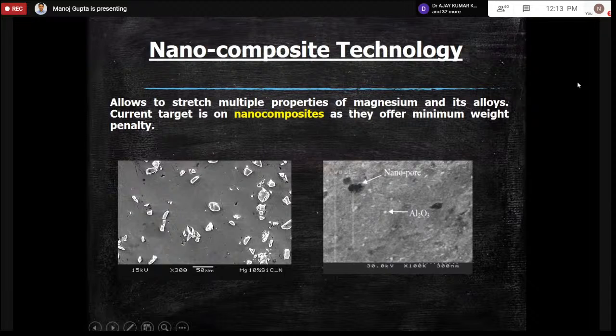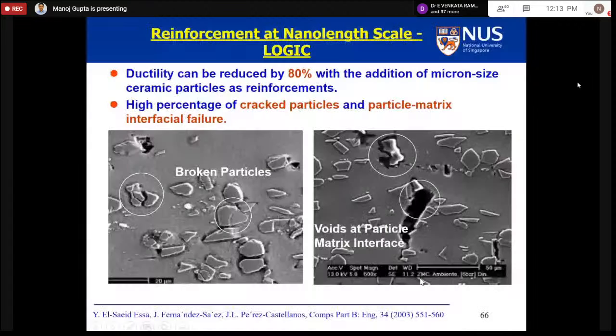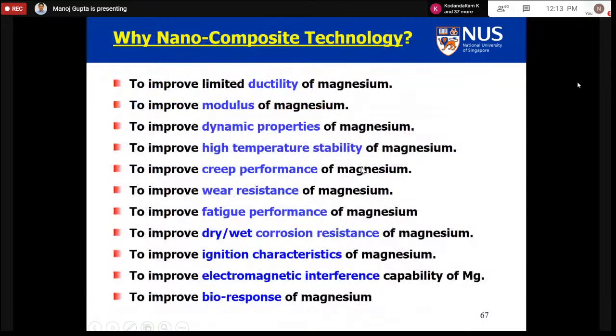So we don't use the micron sized particle which you see in the left hand side image, because they have certain issues of particle breakage as you see in the left hand image, or the debonding which you see in the right hand image. And with that, you can increase the strength, but you don't increase the ductility. The material becomes very brittle. You compromise almost 80% on the ductility and the fracture toughness.